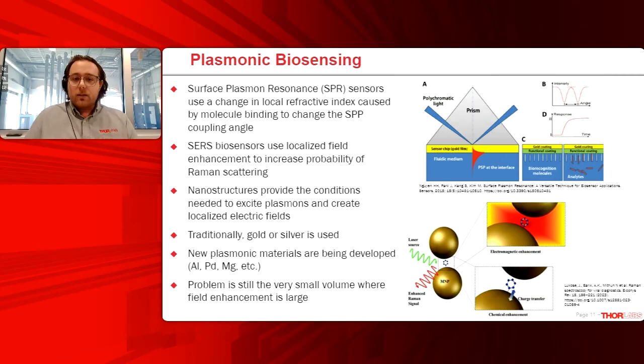Now, plasmonics is a really useful field for biosensing, and this has been well studied for many, many decades now. And there are a few different ways you can use plasmonics to sense materials. The first is surface plasmon resonance sensors. This is where, for example, you can shine light and couple it through a prism onto a gold film. The prism is used to meet the momentum condition needed to excite plasmons. And as you change the incident angle of that light, you'll notice that the light that's reflected all of a sudden drops very significantly.